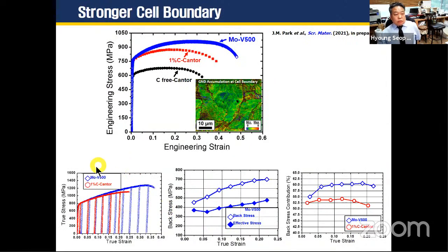So in order to further strengthen the cell boundary and eventually strengthen the additive manufacturing material, I added molybdenum in addition to carbon. These three curves show the Cantor alloy without carbon, all additive manufacturing ones, and carbon-added high entropy alloy and carbon and molybdenum-added high entropy alloys. The carbon-added high entropy alloy exhibited similar yield strength, but higher strain hardening and higher uniform elongation and high ultimate tensile strength, and finally high ductility.